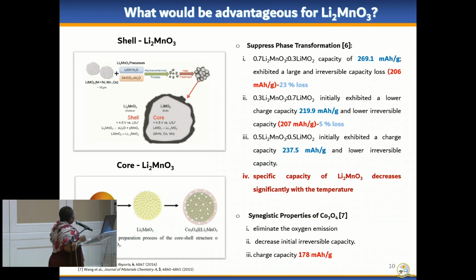So over here, I just wanted to show two examples where we have the Li2MnO3 acting as a shell and where it acts as a core material. When it acts as a shell, the concentration was varied. There are several concentrations that they tried, where they tried the 70%, 30%, and 50%. And it was observed that when the concentration is quite high, it goes back to the issue of irreversible capacity, where about 23% of the capacity is lost. And what was also observed is that the specific capacity of the Li2MnO3 is also compromised at higher temperatures, so they couldn't have it as a shell material.